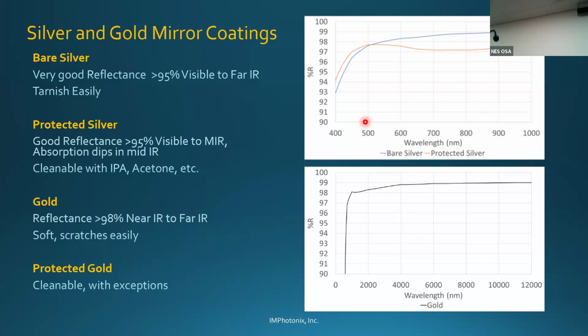And gold has the best reflectance in the infrared, but it's inert. Nothing wants to stick to it, so you usually have to use it as a bare gold coating. You can protect it to a degree where you can do some minor cleaning, rinsing on it, but it's still a soft metal. And to get that 98% with physical vapor deposition, it's going to be a very difficult coating to clean. But it's going to give you very good reflectance in the infrared.